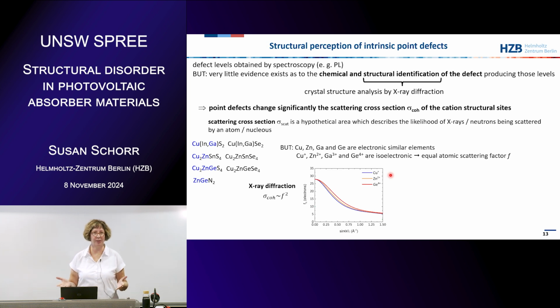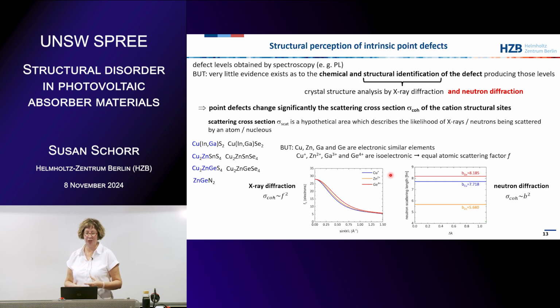And you see the scattering power is very similar, so when you analyze your data later on and would like to distinguish between copper and zinc and germanium, for instance, this will not work if you use X-ray diffraction. That's why we always use neutron diffraction to differentiate these isoelectronic elements, because here you see the neutron scattering length, b, and this is in principle what determines the scattering power of an element. And you see that it's very nicely different for copper and zinc. With all the materials we study here, we have isoelectronic elements, and that's why we always use neutron diffraction. If we did not have these isoelectronic elements, we could use just X-ray diffraction to solve the problem.